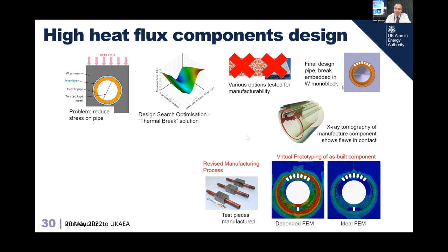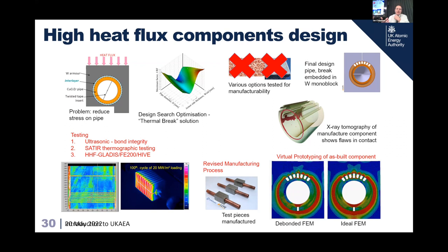And then we put it in a heat flux facility where we cycled it at 20 megawatts a square meter for hundreds of cycles and found that it worked fine. And it could cope with that sort of heat flux, which, as I say, is well above the melt point because of the rapid cooling. So it's sort of, you know, keeping an ice cube in an oven. It is possible. It's hard, but it is possible.